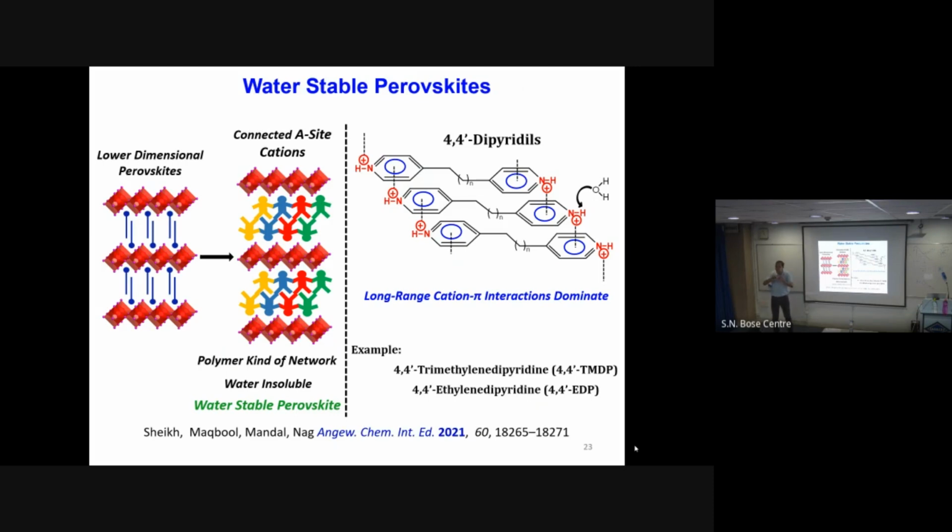It is an ionic interaction between cesium and lead iodide, and that ionic interaction gets disturbed the moment you put water. It's like a sodium chloride salt, it just dissociates immediately. So that's one of the biggest challenges in this field, the water instability of this kind of system. Compared to a 3D perovskite like cesium lead iodide, if you put in the organic ones, the 2D perovskite, the water stability improves simply because there is a hydrophobic chain in this organic molecule. But even then, this improvement is not good enough. You take this 2D system, put it inside a beaker of water,